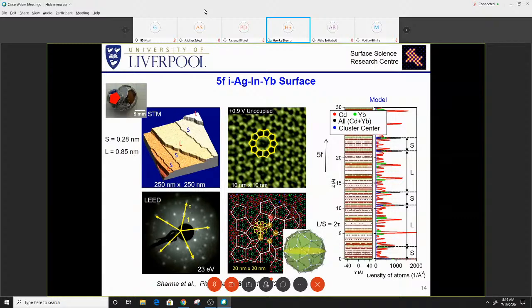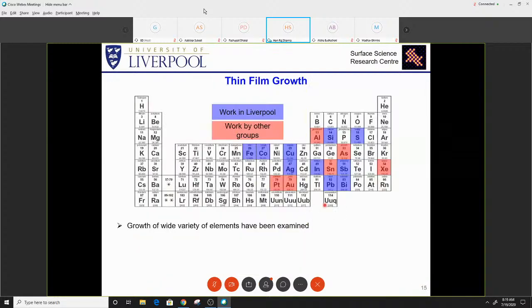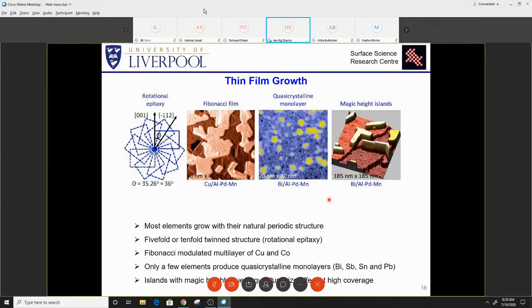Once we have a clear understanding of the clean surface, we deposit various metals. On the periodic table I have marked three elements we studied. Again, just to summarize what happens if you deposit on a quasi-periodic substrate, various things can happen. The first thing: most deposited elements grow in periodic fashion. In this case, I have periodic domain rectangles aligned along 10 directions. These are not real quasicrystals, they are formed by periodic domains.